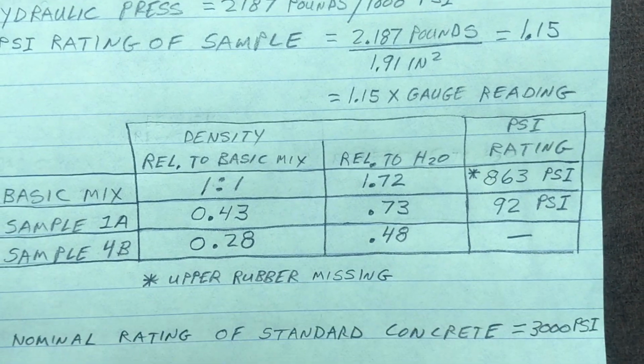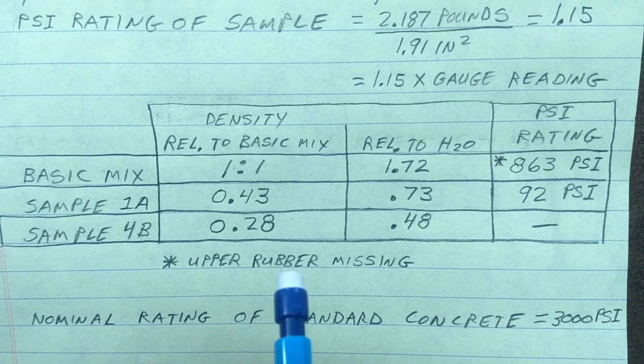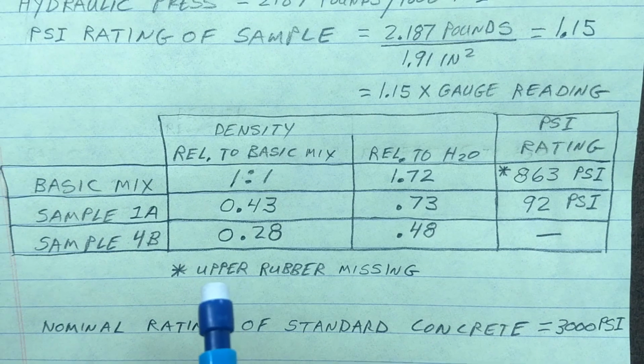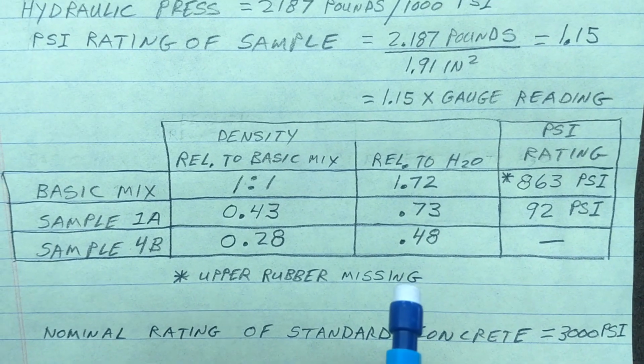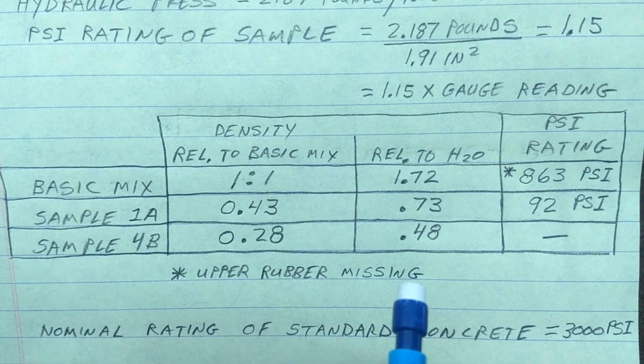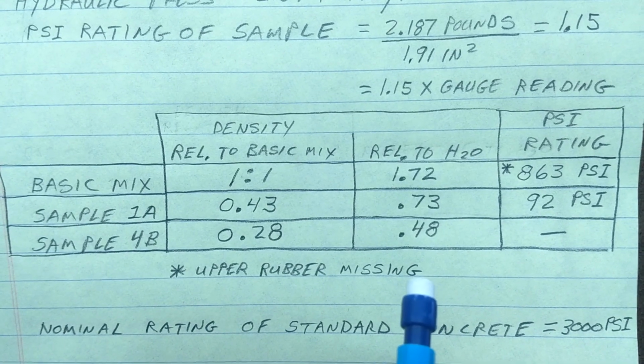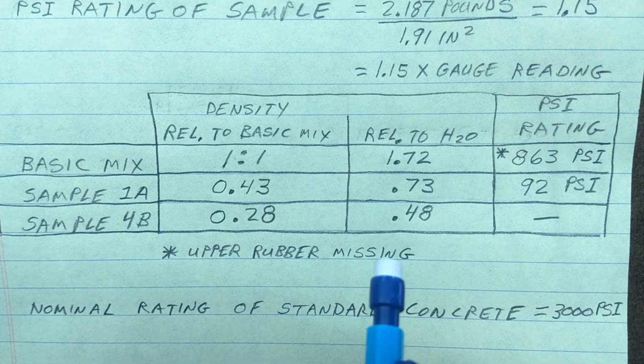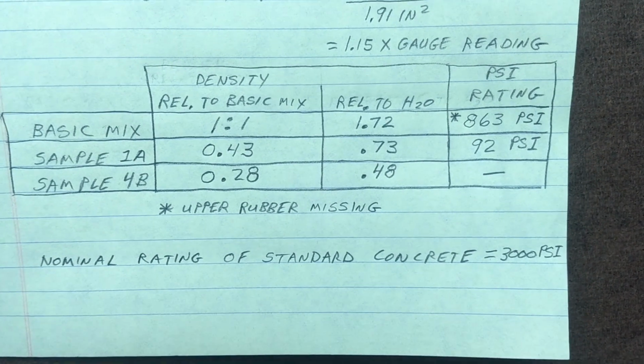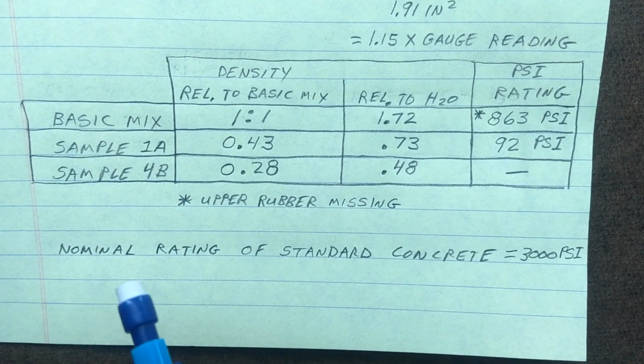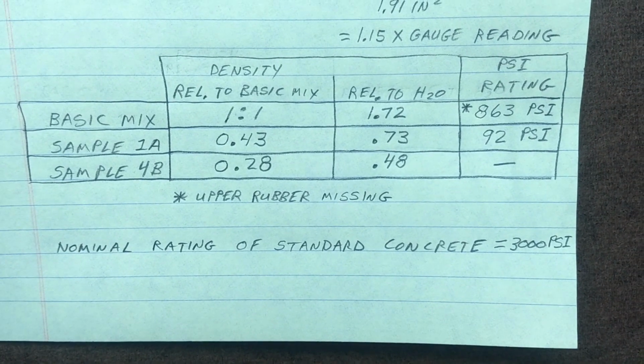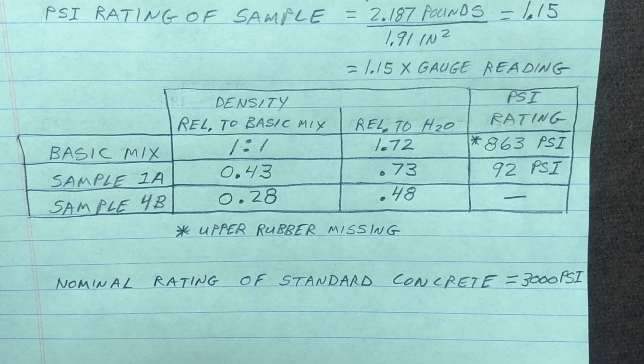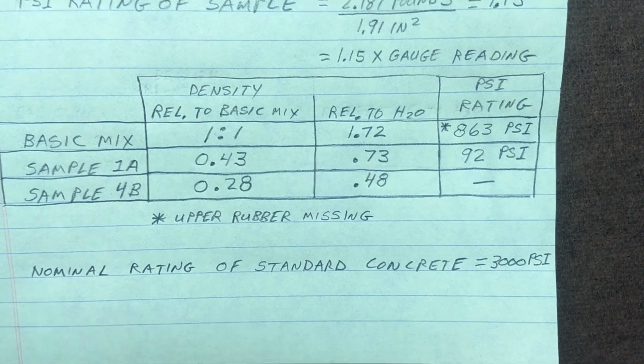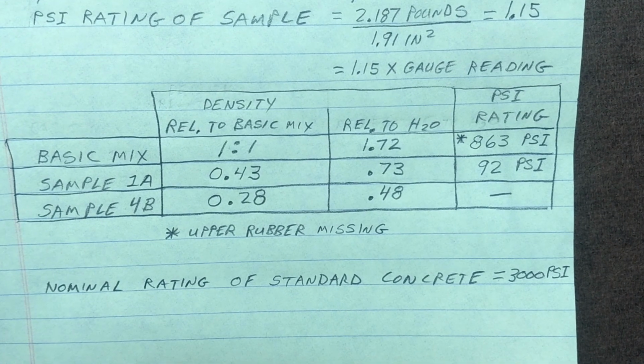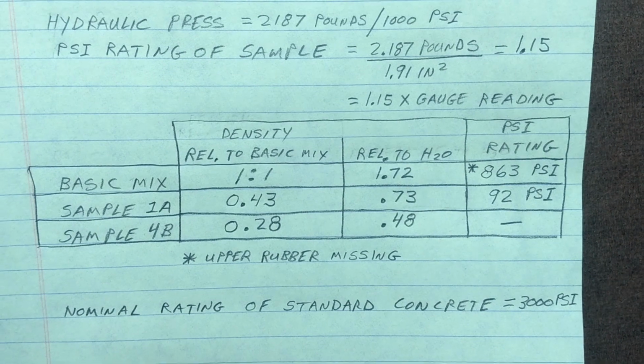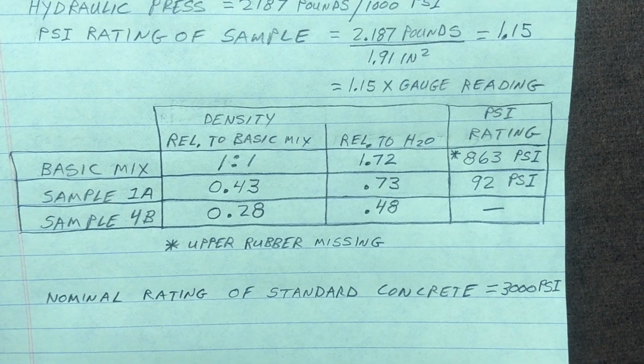Now I have a little asterisk here because in reviewing the video I noticed the upper piece of rubber was missing, and I found it laying back behind the press. So I noticed the sample had sheared along one edge, and that may be due to the rubber missing and us having a pressure point in that area. Now, just as a comparison of everything, the nominal rating of a standard concrete mix is around 3,000 psi. So we'll let everything age another 2 weeks, and then we'll break up some more samples, and I'll have to figure out a better way to attach the rubber to the press. So hang in there and we'll do some more testing.